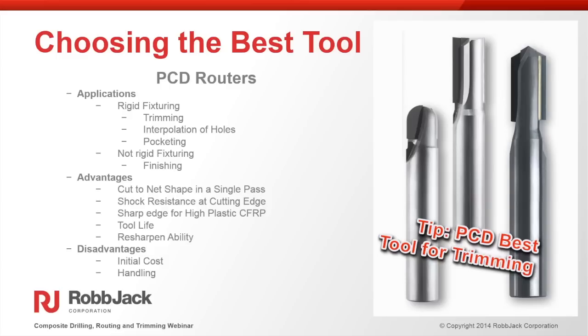When trimming, most people use our PCD tools. The straight flute puts a neutral force on the part, so it's not putting an up shear or a down shear on the part. It works really well if you have that rigid fixturing. They also work really well with the sharper cutting edges for your higher plastic materials. It gives you excellent tool life, and you have the ability to resharpen the tools. The initial cost for the tool is a little bit higher, but the overall cost ends up being a lot lower. So if resharpening or long tool life is important for you, the PCD tends to work out really, really well.